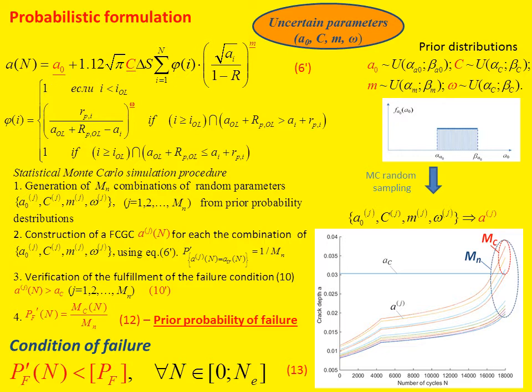In particular, the damage parameters C, M, and Wheeler exponent omega are normally estimated by fitting fatigue test data measured under controlled laboratory environment conditions. Due to potential differences between the test and in-service conditions, there are substantial uncertainties in these parameters. In addition, there is uncertainty in the initial crack size A0 that is estimated during non-destructive testing. Thus, it is better to solve the problem in a probabilistic formulation.